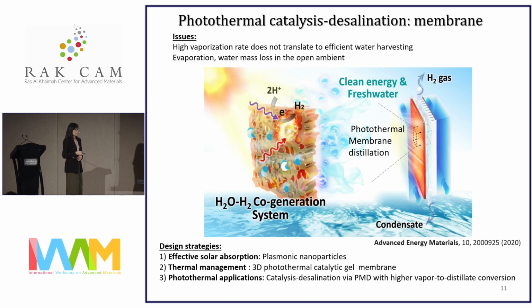Based on these findings, our subsequent work took a slightly different approach. Similarly, we have used photothermal for catalysis and desalination, but this time we have designed a photothermal membrane distillation in order to enable a higher water to distillate conversion. And we have also used silver plasmonic nanoparticles, but instead of suspension based, we have constructed a 3D photothermal catalytic membrane which has proven to have much higher performance.